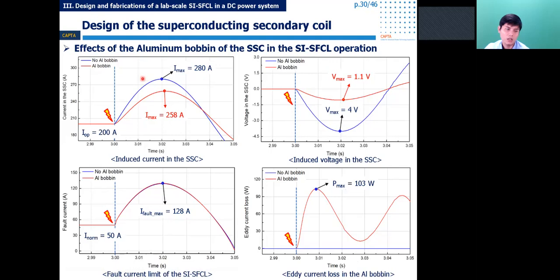So as you see in the simulation result like this, using the aluminum bobbin, the induced voltage and the induced current were greatly reduced during the fault. Because there was induced current in the bobbin, it caused eddy current loss, like this. In addition, the aluminum bobbin didn't affect the fault limit capability of the SFCL, as shown in this graph.